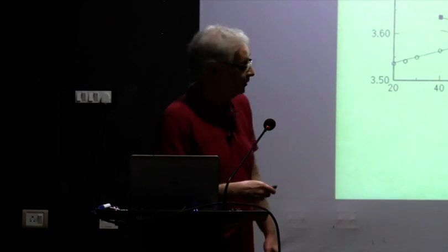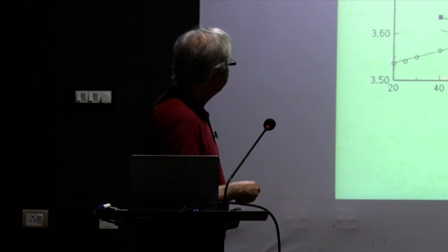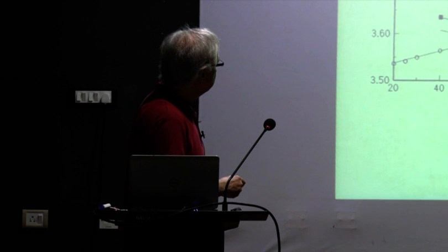Experimental evidence for the stability of Fcc iron. Okay, it runs under this heading. Now, if we take Fcc materials, iron manganese, that's face-centered cubic, iron nickel, iron platinum, ordered, disordered, iron nickel. And if we plot at low temperature the composition dependence of the lattice parameters, what do we see? We see a group of materials here. Those are the iron platinums. When you extrapolate the lattice parameters to 100%, which is X, meaning this is pure iron, then you come to a point which is this.